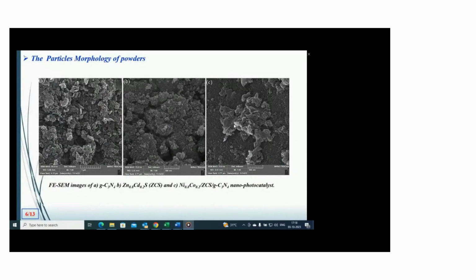This figure shows the FESEM analysis and images of the prepared samples. According to figure A, g-C3N4 shows a layered and porous structure. The porous structure is due to the formation of gas bubbles during the thermal treatment of g-C3N4. According to figure B, ZnCdS shows irregular nanoparticles with an average size of 47 nanometers. And according to figure C, both curved layers of g-C3N4 and ZnCdS nanoparticles are evident.